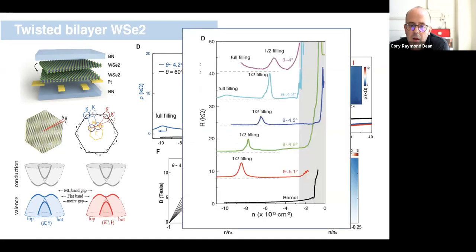Okay. So in this system, as I emphasized at the beginning, we have this broad range of angles over which we might induce some kind of low energy band, and where we might imagine that the bandwidth is less than the Coulomb energy, so we might maintain the opportunity for seeing correlated driven phases. And indeed, we find that that's the case. So here we have a range of twist angles. These are all measured on different devices now, spanning 4 degrees to 5.1 degrees. And what we see is that in each of these devices, by transport, we're able to identify a feature that looks like a resistive feature at exactly half band filling.